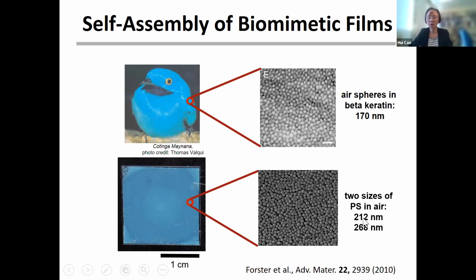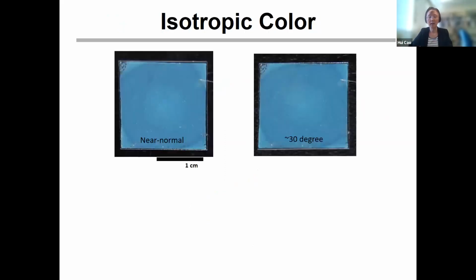The reason we use two different sizes is that if we use a single size, they can assemble into a periodic structure that will give you iridescent color. If we don't want long range order and only want short range order, we have to use two different sizes to suppress the long range order. So that's why we can use this to give us isotropic color. Indeed, if you look at these films from the normal direction or from a 30-degree angle, clearly we can see it's the same color here.